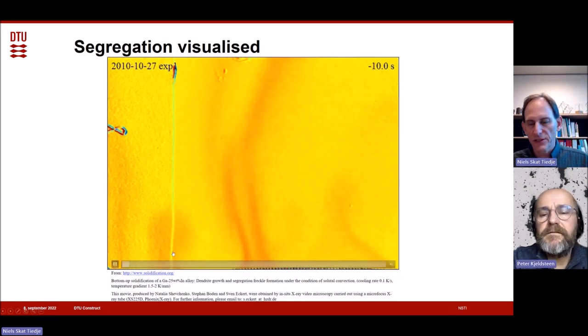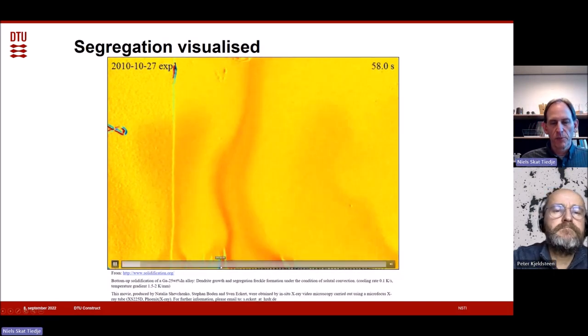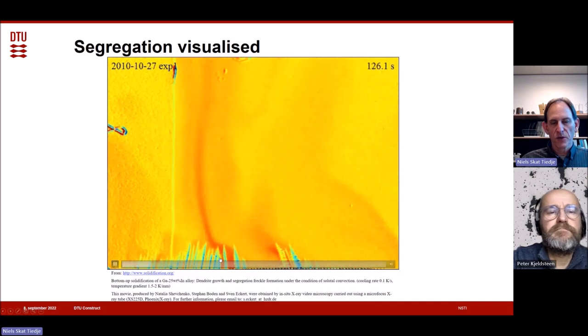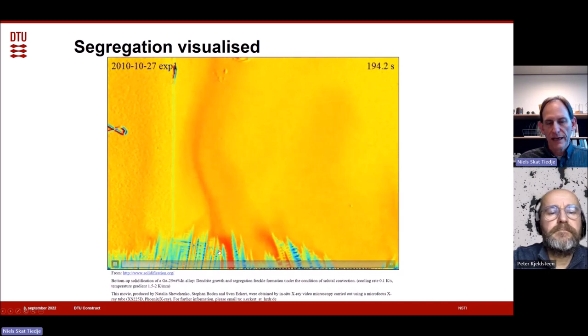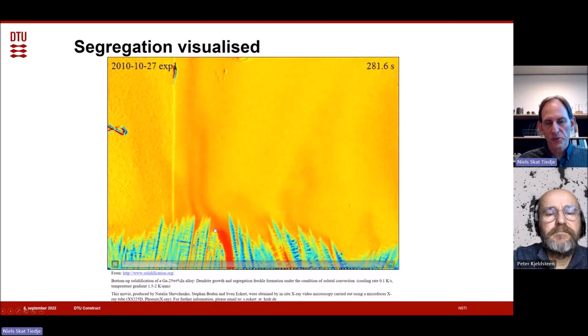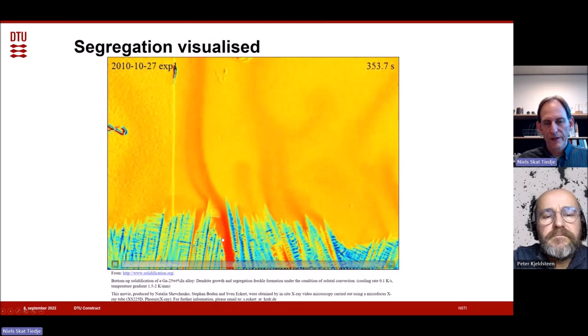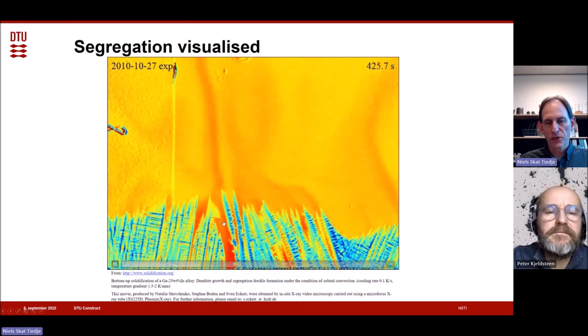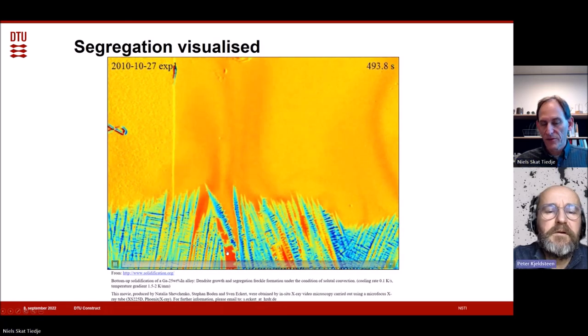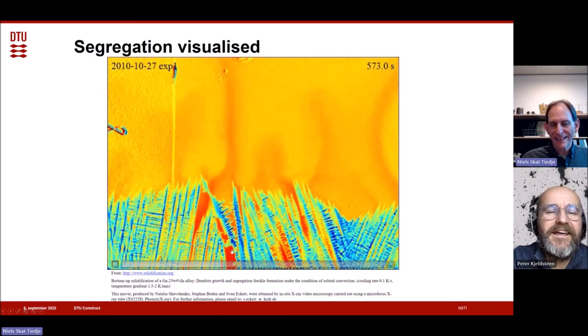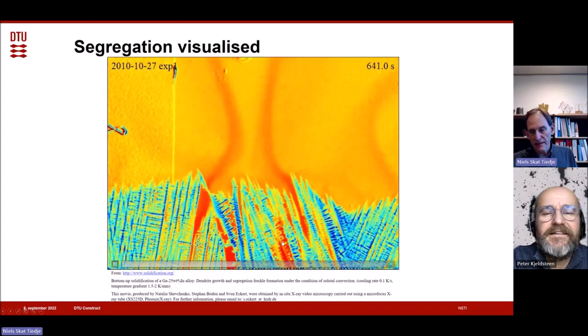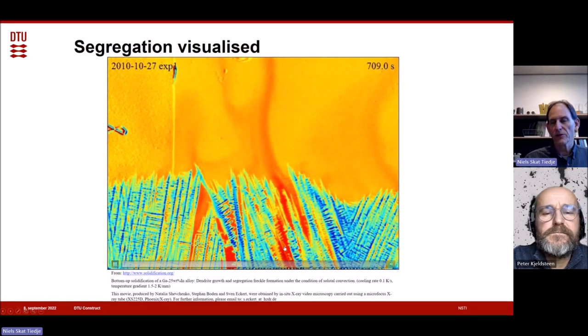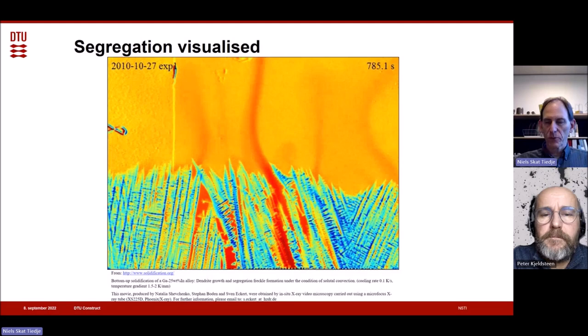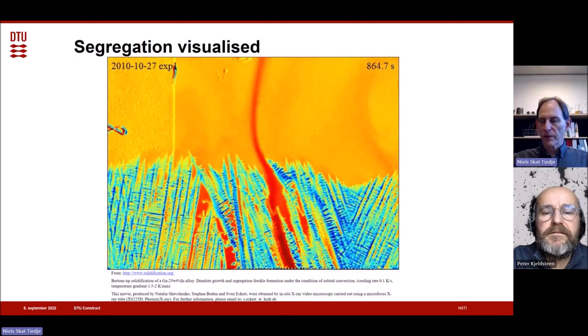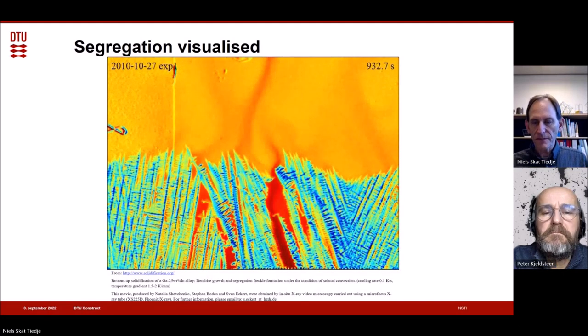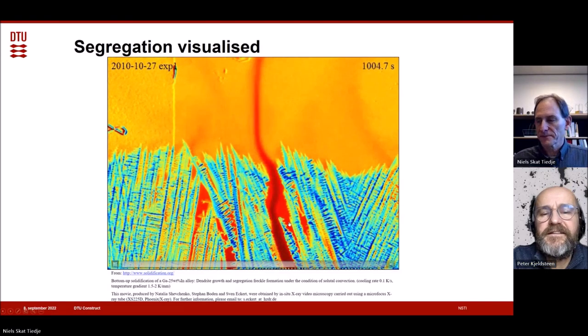And we see the phase diagram in action. Here we see blue dendrites. They have low indium content, just as we would expect. And in the liquid, all the indium is pushed into the liquid. And you can see this channel, there's so much indium pushed in here that the melting point decreases. And we actually see here that the dendrites remelt. They have already solidified, but because there's so much indium there, the melting point decreases and they disappear again.